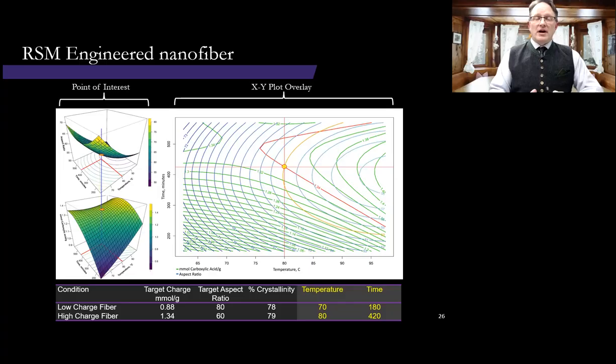So as I stated before, response surface methodology offers a way for us to adjust, in this case, surface charge and morphology while constraining the treatments. But it also allows us to constrain responses. And so we chose to constrain not only the applied ammonium persulfate on fiber, but when the response is percent crystallinity, and then limit our changes to surface charge and aspect ratio. So if you look at the surfaces here, and we select a point on that surface for the target aspect ratio, we can drop down and identify what treatment conditions are required to achieve that.